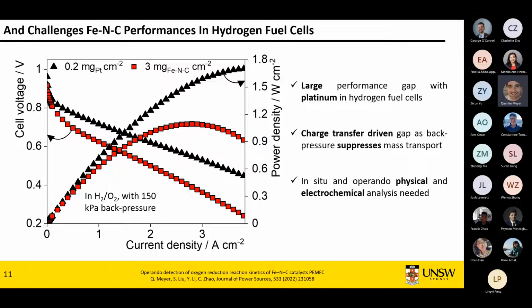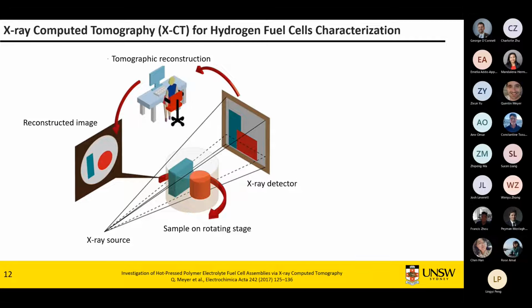The things we do know, however, is that because we apply a lot of back pressure, we have limited gas diffusion problems, and we mostly have charge transfer problems. So transfer of charge to the active sites. And so how do we actually characterize them? Best way, as I was saying, is doing some in situ and in operando measurements and trying to focus as much as possible on the device level challenges.